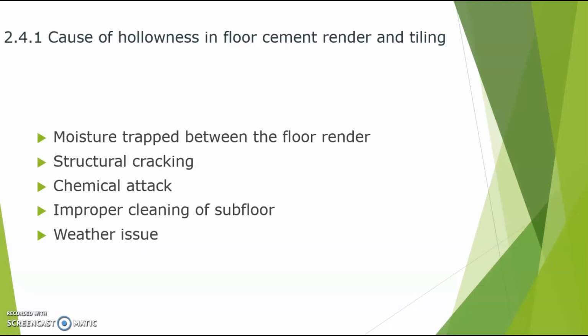While before the starting of rendering work, the worker will clear all the dust, debris, and rubbish that is left in the subfloor. The unclean dust that is left will cause the bonding of the subfloor and outer render to become weaker, as the existence of dust will act as a layer that hinders the subfloor from bonding with the wearing course. As time passes, those layers will start to separate inside and eventually cause hollowness in floor render and tilings.